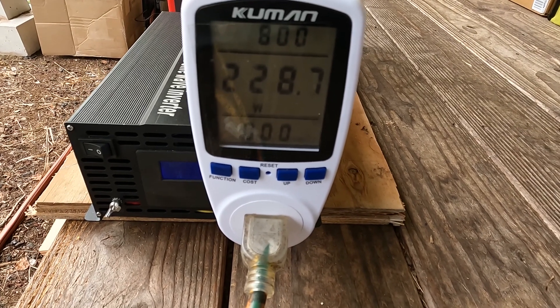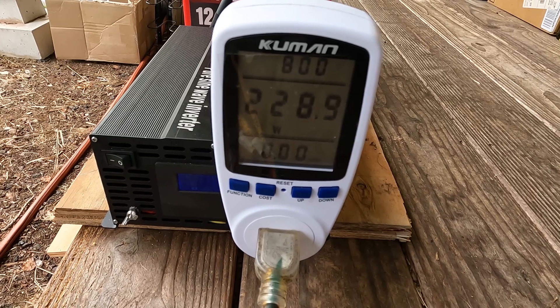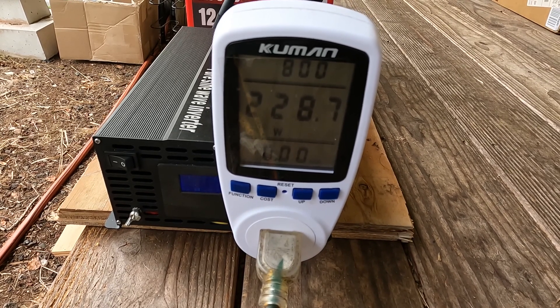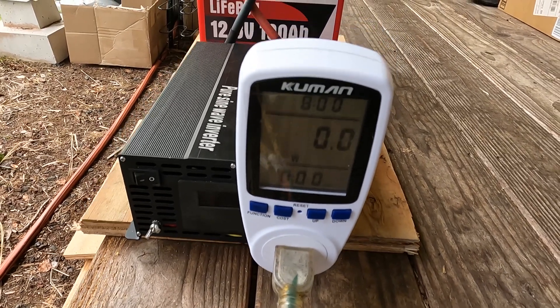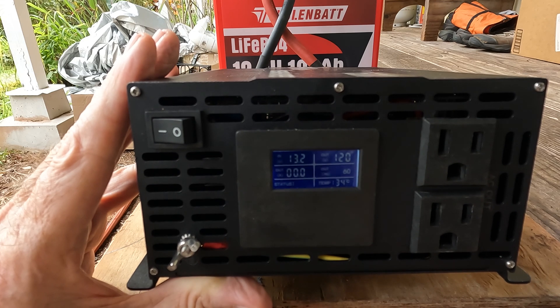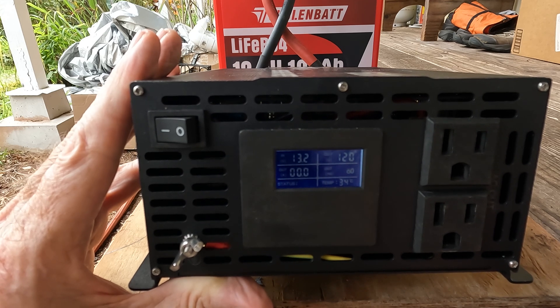At one hour, I'm still pulling a steady 228 watts. It's doing real well, about what I would expect — nothing dramatic, the way we like it. I'm going to come back and do a follow-up test where I take it to my buddy's house and ramp things up to try and pull 300 amps off it and see what it does. I'm liking this battery. I've moved all the water I can, so I'll shut this off now. It's still nice and cool. Although the battery is not totally at rest, I'm reading 13.2 off the inverter — that's about what you'd expect. These batteries quickly drop to 13.2 and hold that for a long time during discharge. The accurate way would be to have a battery monitor and let it rest about three hours for a very accurate read.